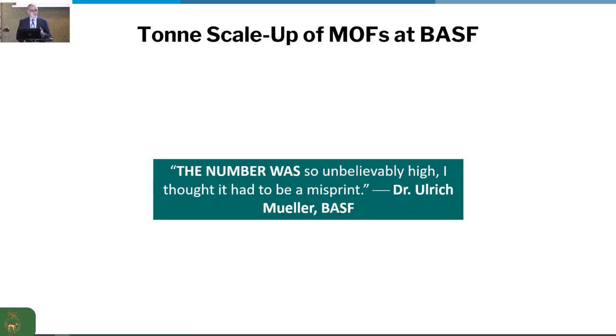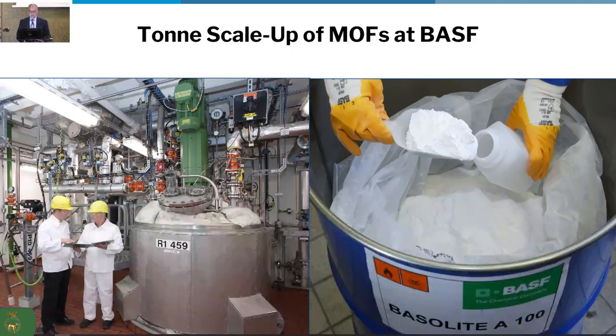And fortunately, it was quite reproducible, and they were very impressed by these high surface area numbers and started a very nice and productive collaboration that lasted for 17 years. And during this, they showed that in fact MOFs could be made in multi-ton quantities, and they're not just laboratory curiosities. This was a very important development at the time.